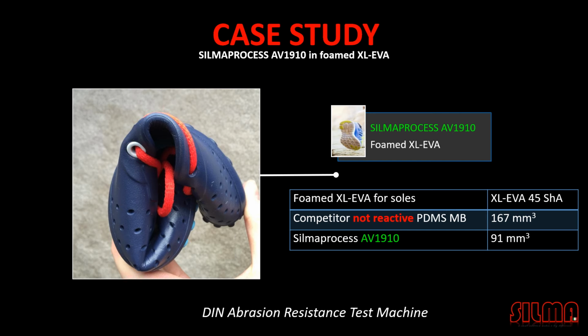High or extra high molecular weight polydimethylsiloxane, in this case an extra high molecular weight rubber, that is very difficult to handle and to use. But in this case, this high molecular weight, when you mix it into your compound, will have a physical entanglement with your polymer. So even if there is no chemical bond between the polysiloxane and your polymer, you will have, in any case, a kind of physical bonding. It's like spaghetti: you cannot have one single spaghetti because they are all mixed together in a kind of coil. So this is a phenomenon due to the high molecular weight. Or we did also a reactive processing in our extruders, producing a two-dimensional or three-dimensional structure of polysiloxane chains.